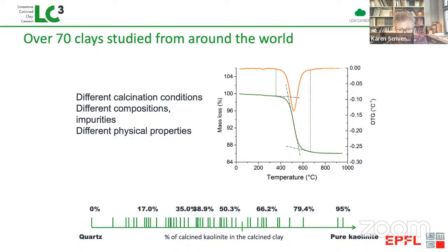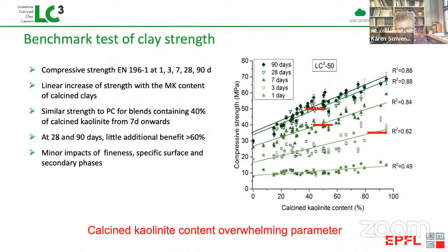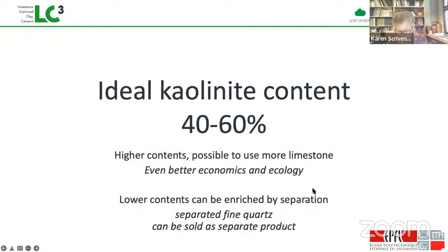We've now tested more than 70 clays from around the world. We see in terms of strength development that this kaolinite content is the key factor. And the red lines on this graph indicate the reference strength of the plain OPC. You can see that by 7 and 28 days, we only need a kaolinite content of about 40%. So ideally, you have 40 to 60%.